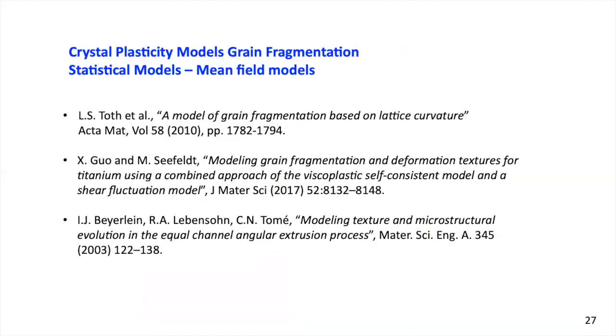And today there is a lot of activity in the crystal plasticity community to model crystal fragmentation. And in fact, there are two types of approaches. Like in so many texture models, you have an approach which is based on mean field behavior, and these are statistical models. I have listed here three statistical models that are reported in the literature. We have worked with the model of Professor Toth from Lorraine University in France.